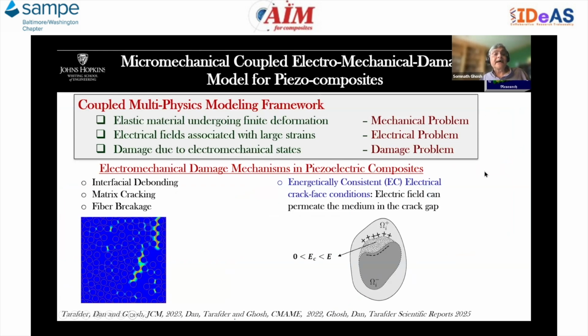So a little bit about the micromechanical analysis. The micromechanics, as you can understand, consists of the fibers or multiple phases, the fibers in, let's say, a polymeric matrix. And in this particular problem, I'm modeling it as a finite deformation elastic matrix material. So this is for the mechanical problem. For the electrical problem, we have electrical fields associated with large strains, and damage due to electromechanical states because of interfacial debonding, fiber breakage, matrix cracking. As well, for the electrical field, we have an energetically consistent electrical crack face condition here, where the electrical field can permeate through the medium in the crack gap.